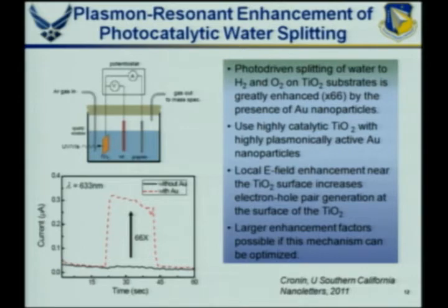If you put down gold nanoparticles, those have plasmon excitations in the visible. Putting down gold nanoparticles on the TiO2 substrate, you can excite this in the visible, create electron-hole pairs that start this chemistry going. And you saw an increase of a factor of 66 in the oxidation of water on these TiO2 electrodes. And that's in a kind of crude system, very unoptimized.